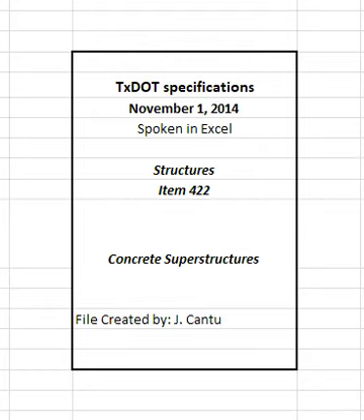4.8.2 Burlap mats. The burlap used for interim curing may also be used for final curing if kept continuously wetted and completely covered with plastic sheeting. Overlap plastic sheeting and weigh down sufficiently so air cannot get under the plastic. 4.8.3 Burlap polyethylene mats. Place these mats over soaker hoses or other similar methods to keep the concrete surface wetted for the duration of the curing period. Overlap the mats and weight down sufficiently so air cannot get under the mats.